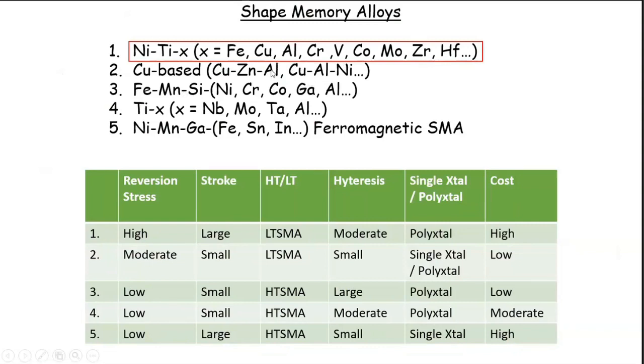Now, nickel titanium is an ordered intermetallic, and this will be seen in a picture later when I show it. It's like a B2 (CsCl) structure, as they call it, and the nickel and titanium occupy their own respective positions. So when you add iron or copper or aluminum, it either substitutes for nickel or it substitutes for titanium. I think I'll discuss it a little later when the slide comes. And such is the case with copper, also copper-based alloys. This is also an ordered intermetallic, and so is nickel manganese gallium.